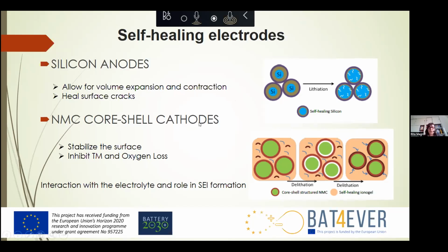On the other side, for the cathodes, we propose NMC core-shell particles, and cathodes also have problems, so we study the protection of the cathode surface through self-healing binders. In the case of the cathodes, it is necessary to stabilize the surface, inhibiting transition metal and oxygen losses, and any chemical reaction that can modify the surface and lead to loss of material. Also, it's very important for the binder to have a good interaction with the electrolytes and a good role in the CEI formation.